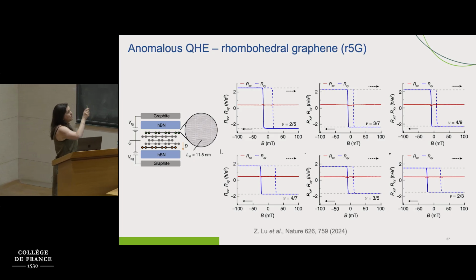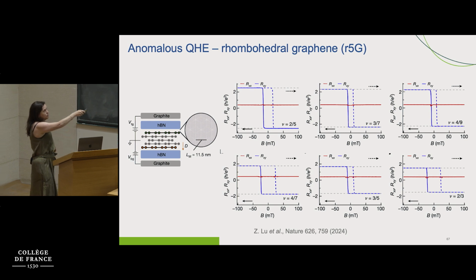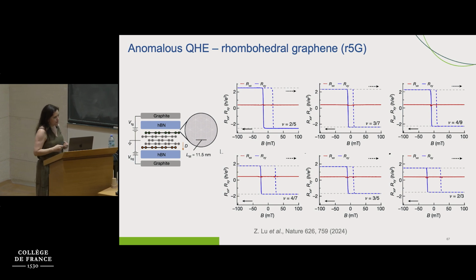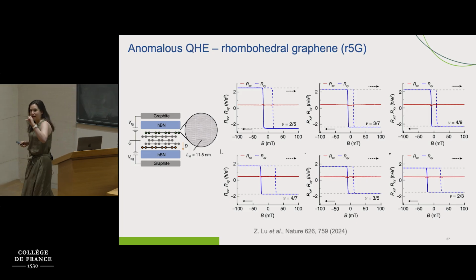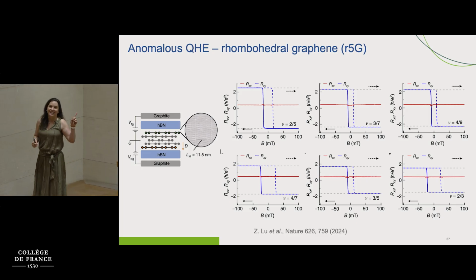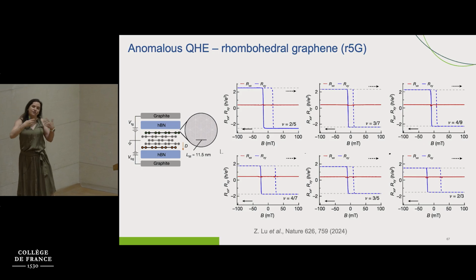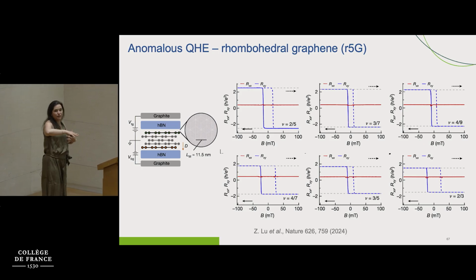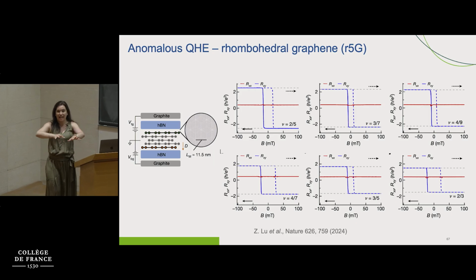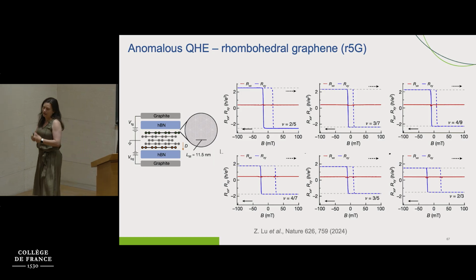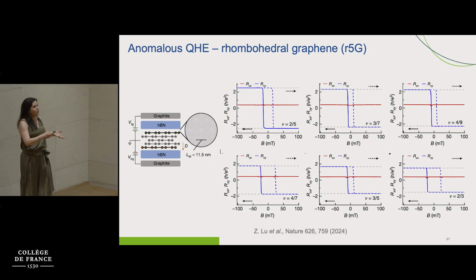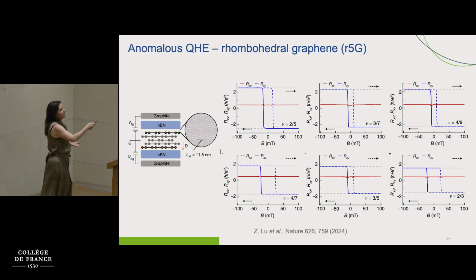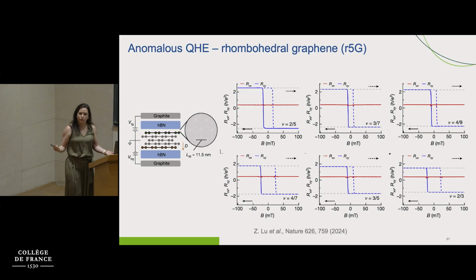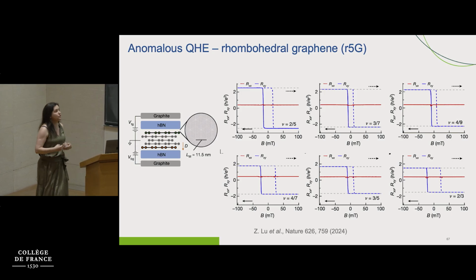What is very important to keep in mind when you look at these hysteresis loops is: remember twisted bilayer before? It was not that clean. It had a bunch of jumps in the middle. The reason for that is because you have angle disorder in twisted bilayer graphene. You have a lot of different angles in the same sample, which are going to give you different effective magnetizations. However, rhombohedral graphene seems to be an extremely clean material, where we have a Moiré superlattice which, as it is formed with boron nitride and not with another graphene, is way more stable.